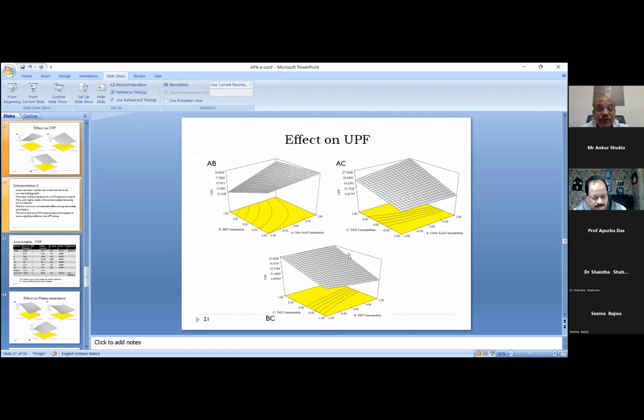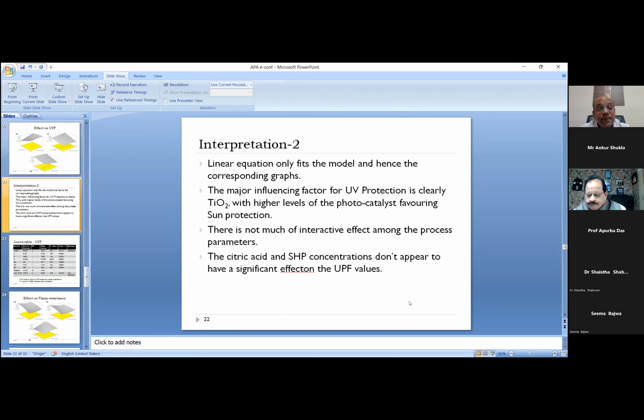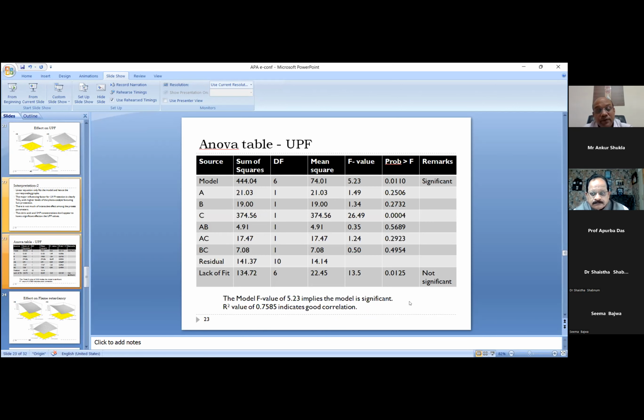UPF factor. Okay, so here also you can see in BC also you can see that there is a significant increase in the UPF factor as the TiO2 concentration is increasing here. So this is how it is increasing, and hence the UPF factor is also high. So this is the interpretation. And TiO2 is the lone contributor here for higher UPF. And the model is significant as the table shows.